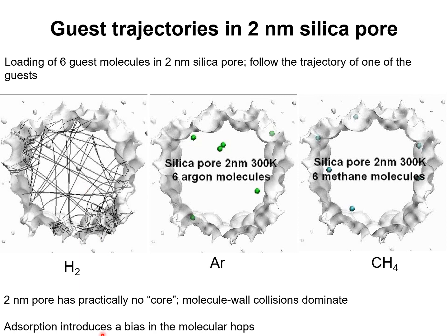This is for hydrogen, and we see that the hydrogen molecules collide with a rough silica surface and experience a random trajectory, and the angle of incidence when a molecule of hydrogen strikes the wall bears no relation to the angle at which it gets reflected from the pore walls.